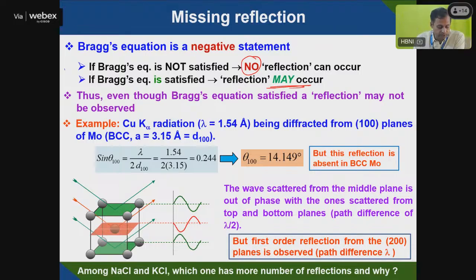For example, you will see here, this is a molybdenum BCC structure. You can see that green wave, this plane is coming here, diffraction. And at the center there is a red plane. If you see that the wave started from the middle plane, this is the first top plane, and this is the bottom plane, that green one. So they are in phase. If these are in phase, you will be able to see constructive interference, and you will be able to see a perfect peak. But in the middle plane, you see here, that is in the opposite phase. The phase difference is not lambda; the phase difference is lambda by 2 here.